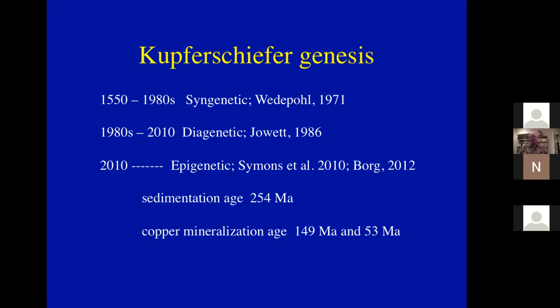It has been proposed to be originally syngenetic deposition of copper and other metals directly out of seawater, and that fell out of favor in the 1980s, and then it was assumed to be diagenetic, and very shortly after the deposition of the sediments. But in 2010, Symons and Borg and several other colleagues established that the copper mineralization actually occurred in two episodes, one at 149 million years that was almost 100 million years after the sedimentation age of the Permian sediments, and then again at about 53 million years. So it ends up that there is now evidence that this is a truly epigenetic deposit imposed upon these rocks long after they had become rock.